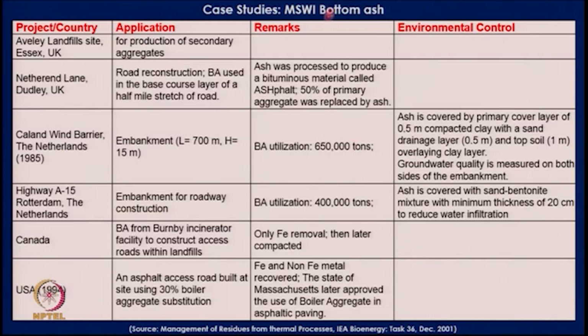If one looks at case studies for reutilization of incinerated bottom ash, we find that often it has been used for production of secondary aggregates or as part of the base course in road construction. 2 examples of embankment construction in Netherlands reported in the 80s talk about large utilization of bottom ash, but it's important to note that wherever bottom ash was used, a compacted clay liner was put over it and also a sand drainage layer in an attempt to keep the water out of the bottom ash which had been placed in the embankment, and groundwater quality was measured intensively on both sides of the embankment. And so is the case in the second example, where a sand bentonite mixture was used on top to minimize the infiltration of the rainwater reaching the bottom ash.